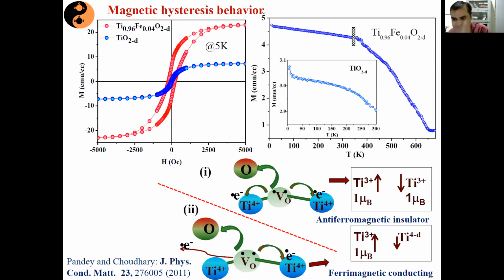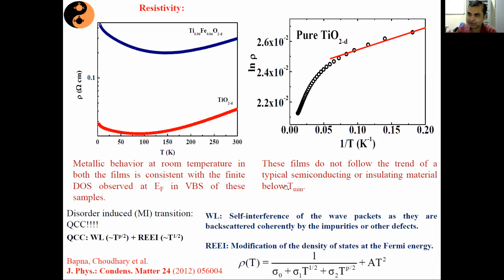How do I confirm that this is the only way of having charge carrier mediated magnetization, not otherwise? Then what I did, we killed this oxygen vacancy. So how do I kill that oxygen vacancy? I killed that oxygen vacancy by annealing the film in the presence of ambient oxygen. And when you anneal the film in the presence of ambient oxygen, it made up for the oxygen vacancy. Wherever the oxygen vacancy was there, oxygen atoms went and took its place. So it got rid of oxygen vacancy. That means those two free electrons which were available to us earlier are now no more available. So the system should behave like an insulator, not like this metallic behavior. And also, since I have decreased the carrier density in the system, the magnetization should also come down.